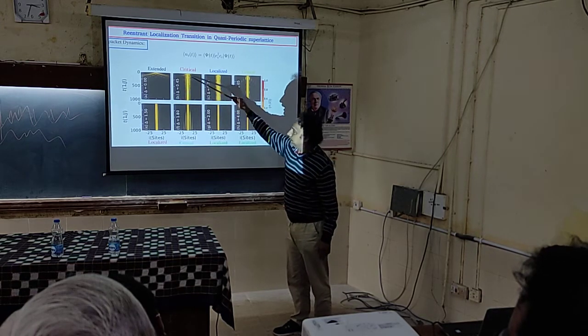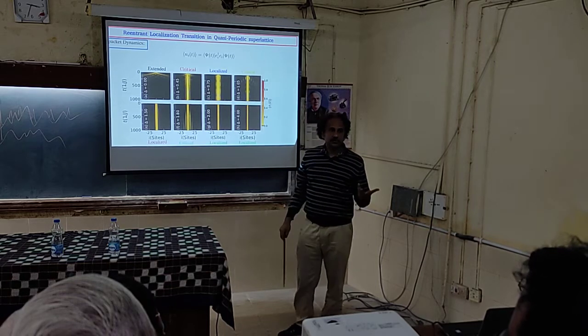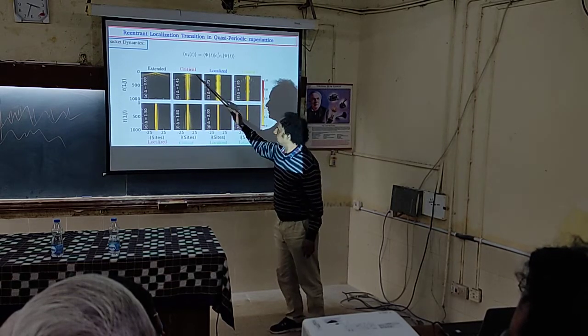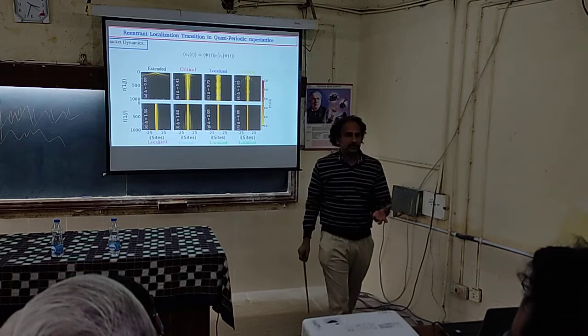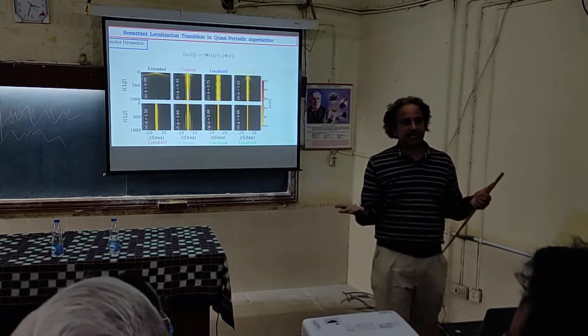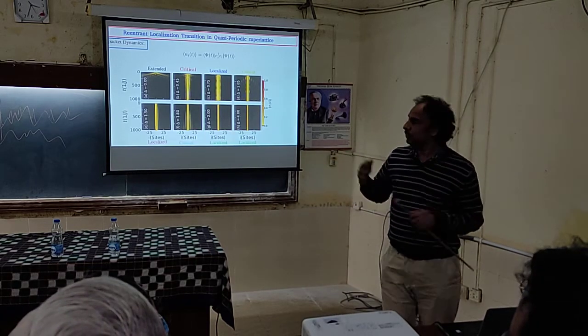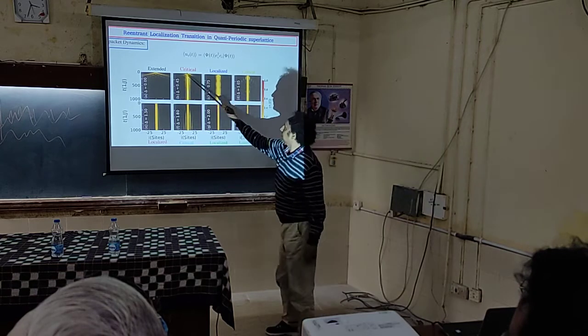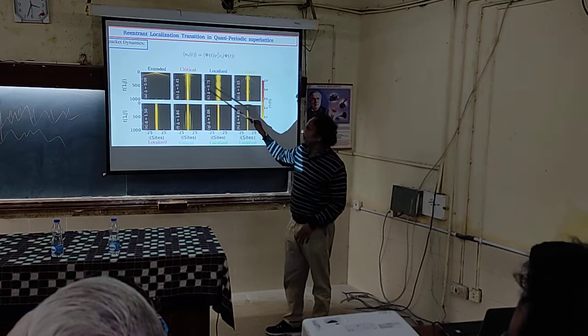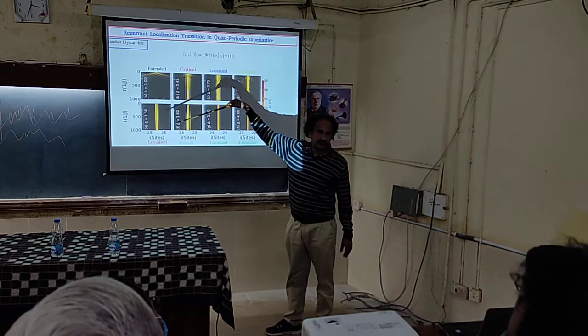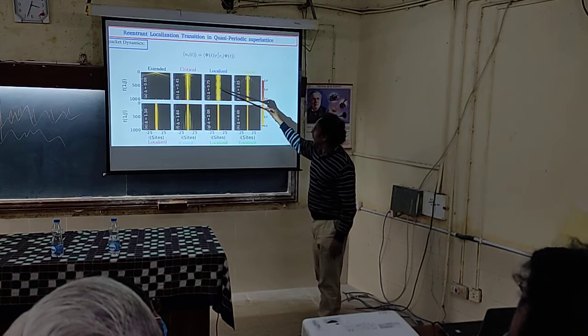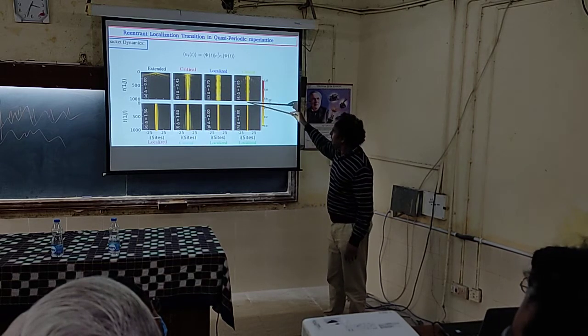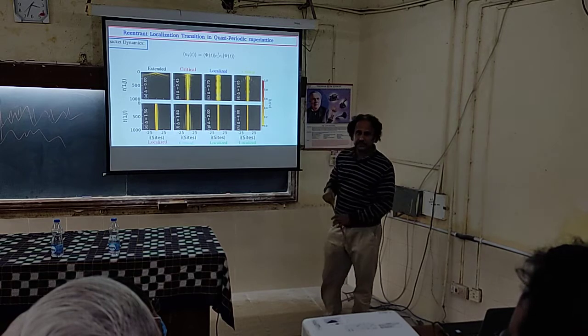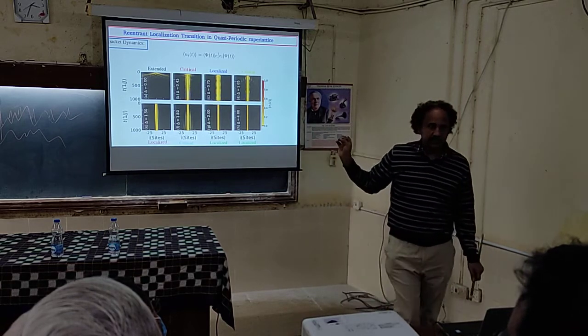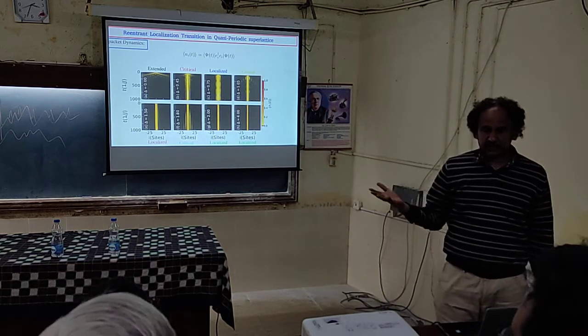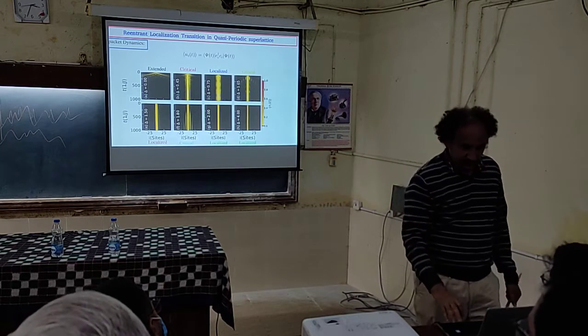But if you go to the critical phase, there is a bimodal distribution. Some of them are spreading fast, some of them remain at the center, because it is an intermediate phase. Some states are extended, some states are localized. Those that are extended spread and go to the boundary. Those that are localized remain at the center. So, a bimodal distribution. Again localized, critical. Some of them are localized, some are spreading. So this can be seen experimentally. Clearly, there are state-of-the-art experiments where this is easily seen.